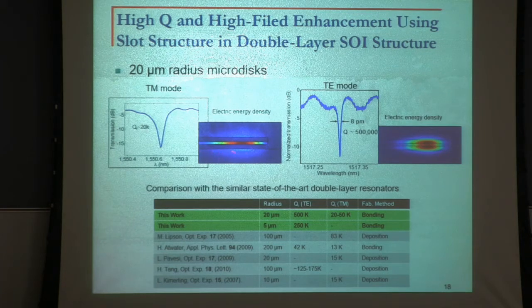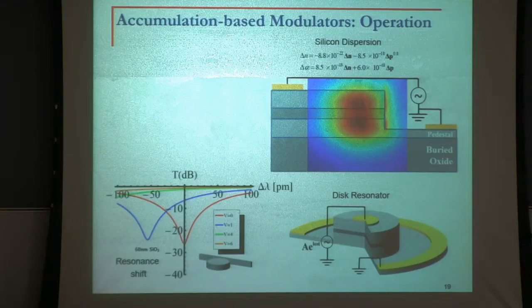This is the transverse electric mode, and this is the transverse magnetic mode. Some have most of their energy in the middle region, and the other one have the TM and TE. TM has most of the energy in the oxide between, and then TE has most of the energy in silicon. So this is an excellent platform for modulation tuning when you want silicon property to kick in. This is an excellent material if you want to etch oxide and replace it with a material to sense, for example, where most of the energy is there. We use TE.